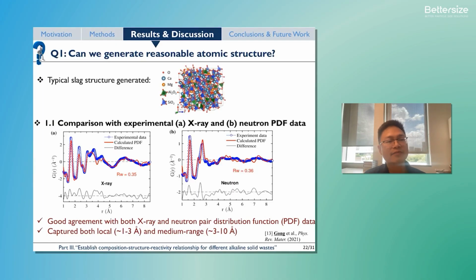Now, let's check out some results. Firstly, here is the typical atomic structure generated for a typical slag, which is an industrial byproduct from steel production. Based on these structures, I have calculated the X-ray and neutron scattering data and compared them with the corresponding experimental data. As you can see, there are good agreements for both the X-ray total scattering data on the left and neutron scattering data on the right.